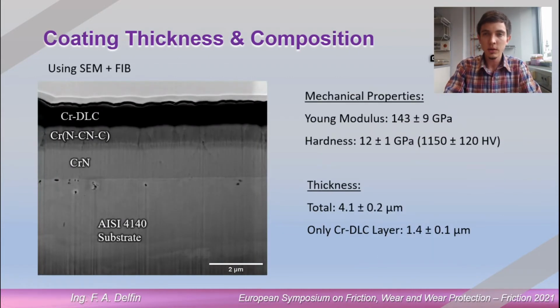So here we have a cross-section obtained with focused ion beam. This is the substrate. Here you can see the chromium nitride layer and also the gradient in the chromium compounds from chromium nitride, chromium carbonitride to chromium carbides. And on top, this black part is the chromium doped DLC coating. The overall thickness of this is around 4 or 5 micrometers.